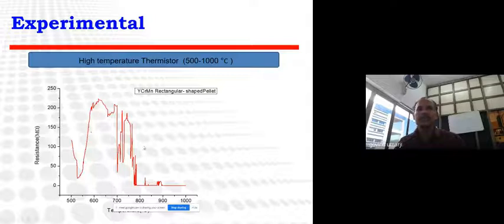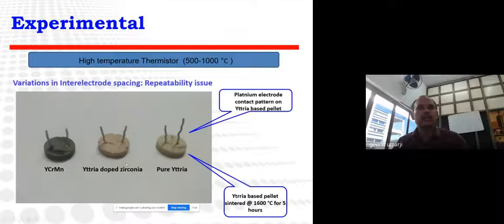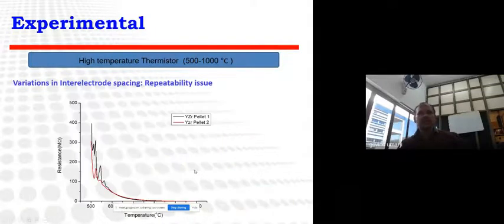After preparing the pellet-shaped things, we also found that yes, it shows sensing, but stability is very poor, contact is very poor. So we again rethought that. We started preparing a standard size pellet, but when connecting the electrode, we found that repeatability is an issue. Repeatability is the common issue for that, because each and every time the electrode has a different location, but it shows sensing properly.